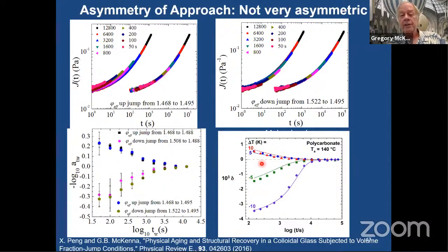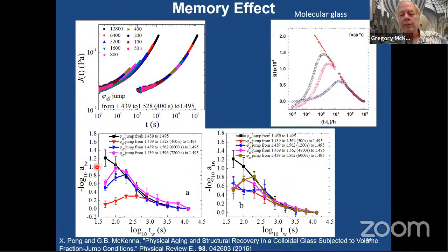And a question that needs to be asked is whether or not this is because in colloids we're doing constant concentration, whereas when I do a temperature jump I'm doing constant temperature, but the volume is changing. So these are isobaric, whereas the colloid experiments are in a sense equivalent to isochoric experiments. And so in principle, what we've learned from the colloids is maybe we need to more closely look at the possibility of doing isochoric experiments in molecular glasses. We also get a memory effect. It doesn't seem quite as strong, but the data are much noisier than Kovacs's beautiful work.